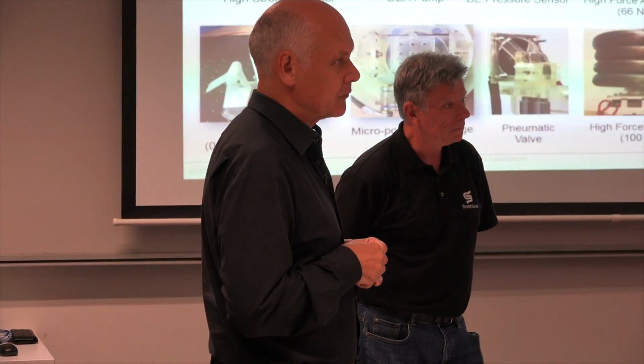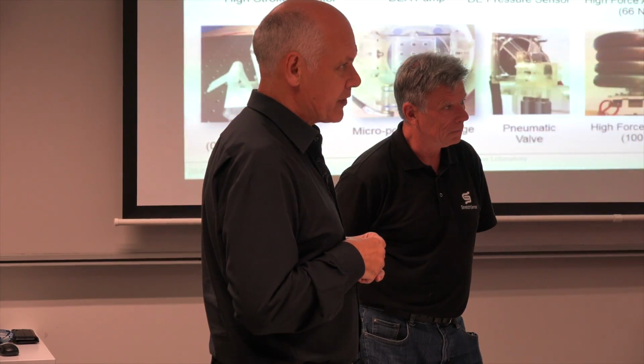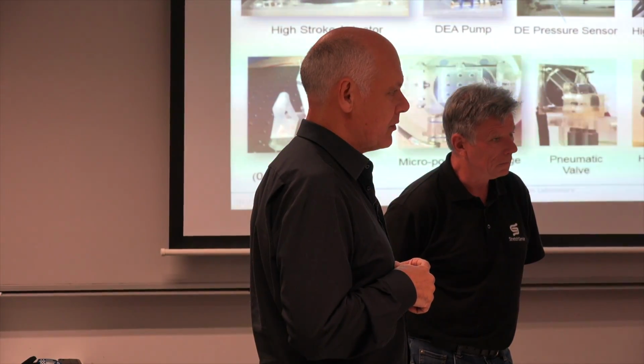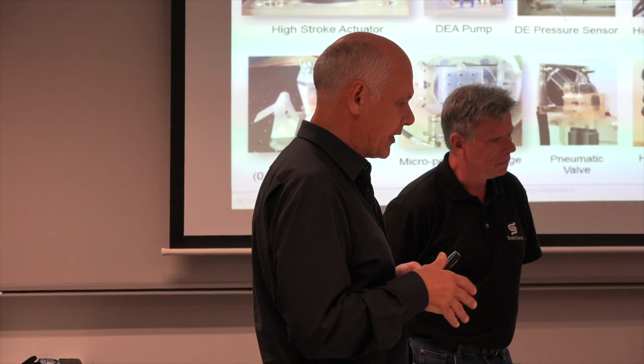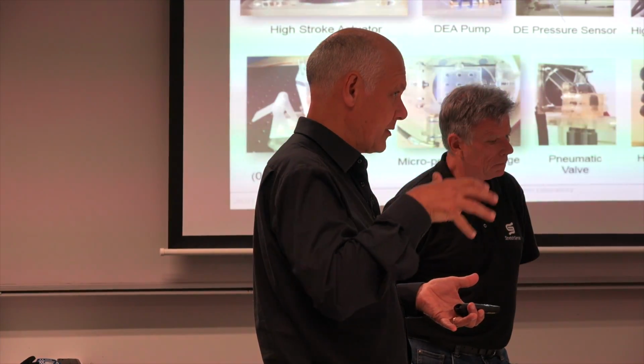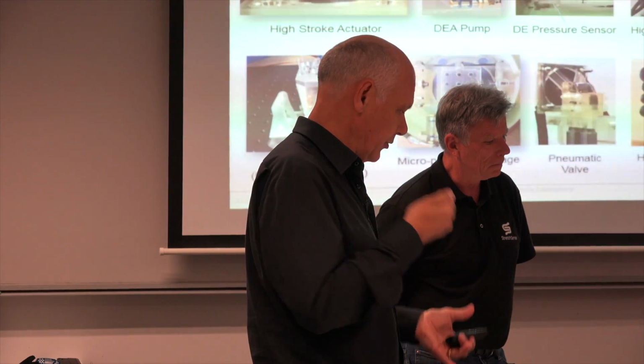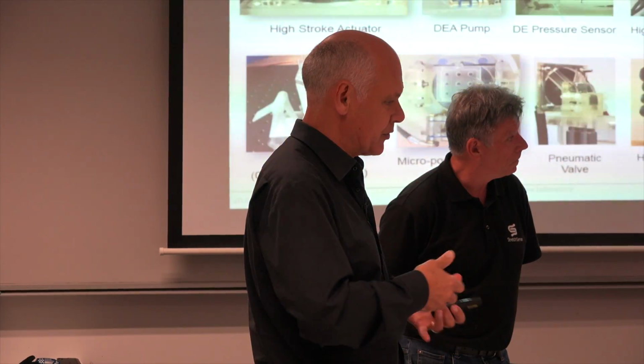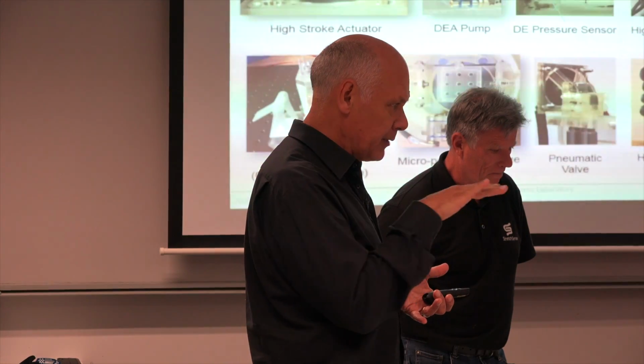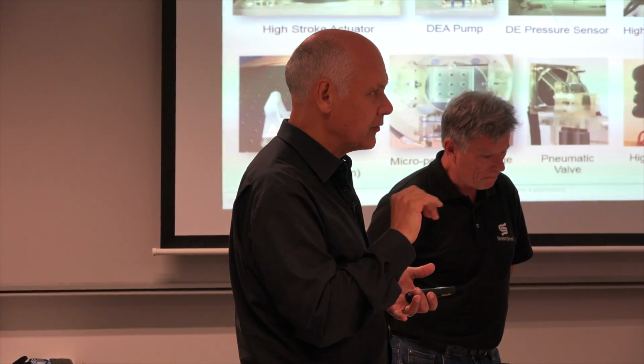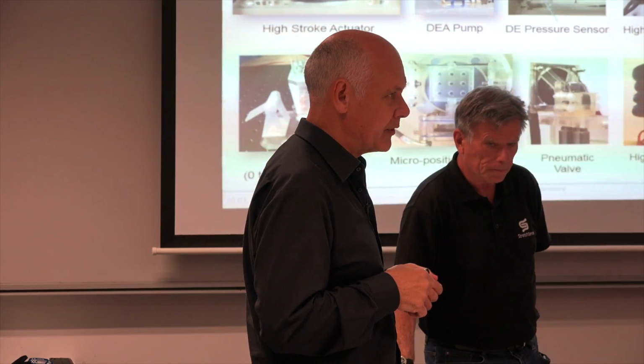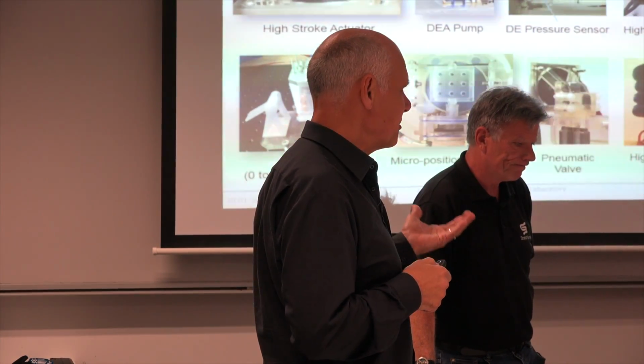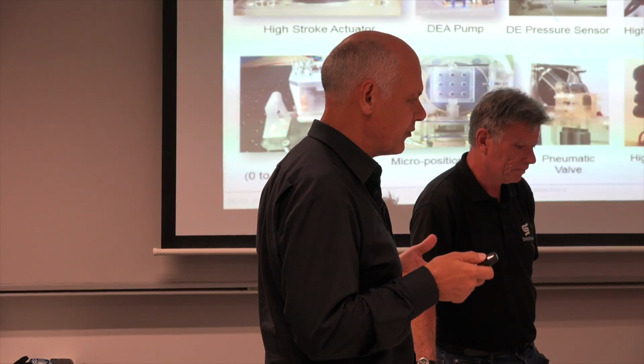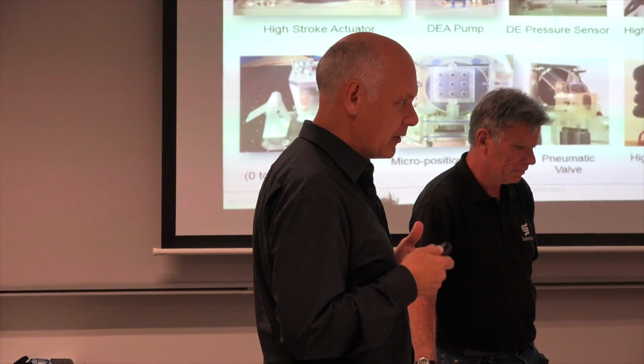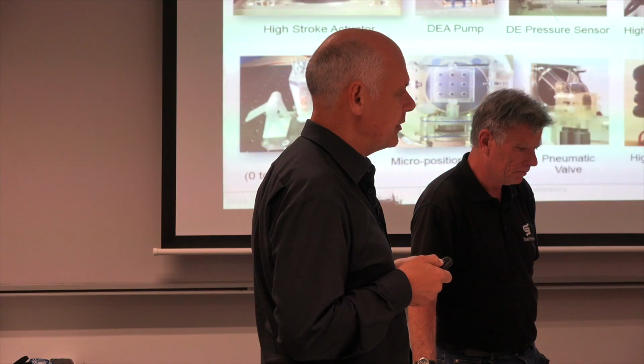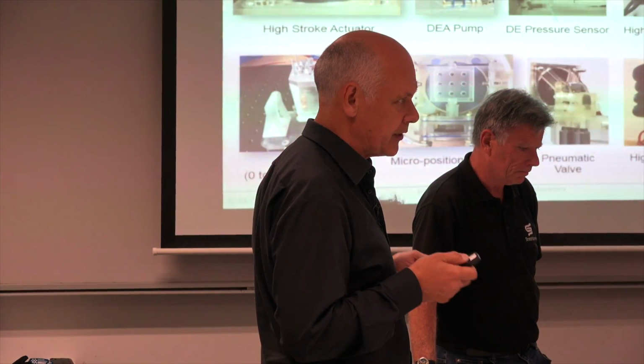And what's the number of cycles to failure of the... For an SMA, it completely depends on the loading, like with everything. You can get up to, let's say, 1,000 megapascals of stress from the material when you load it, and probably do that 3 or 4 times, and then it's plastically deformed. But if you limit it to, let's say, 150, 200, 250 megapascals, you can easily get 1 million cycles from it. And there has been a recent Science paper where colleagues have shown that if you add quaternary composition elements to it, you can even get 10 to the 7 cycles without any change in the material.